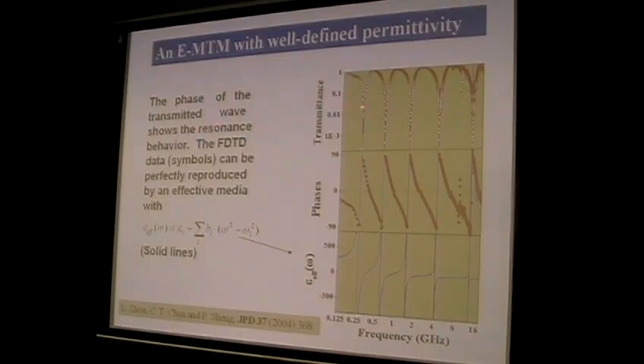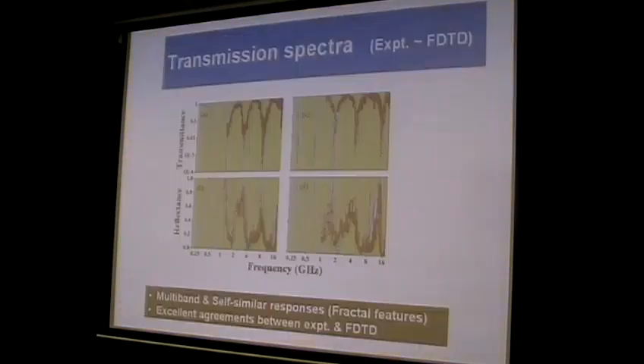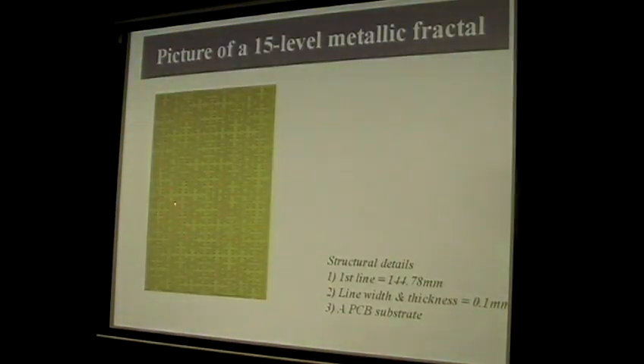To understand this very particular, very intriguing phenomenon, we construct a model to characterize this response. We notice that although the structure is very complicated, the wavelength is much longer than the structural details. So that's exactly the situation where the concept of metamaterial can apply.